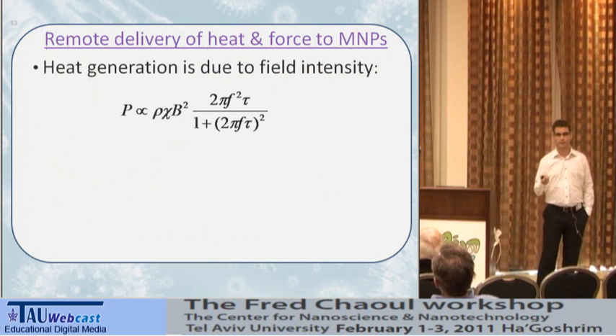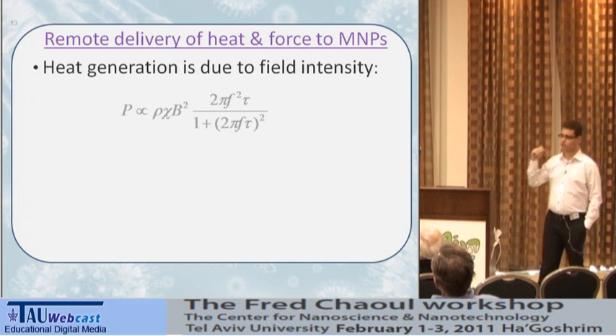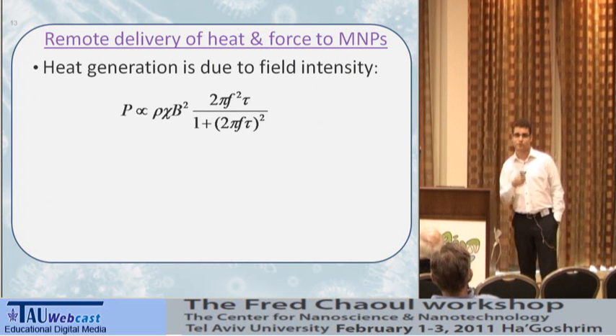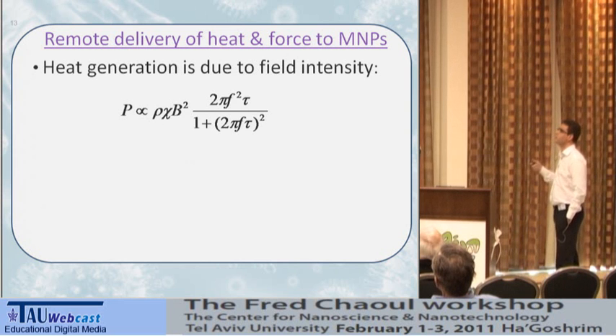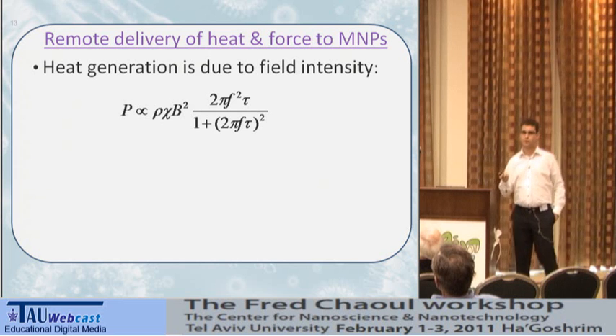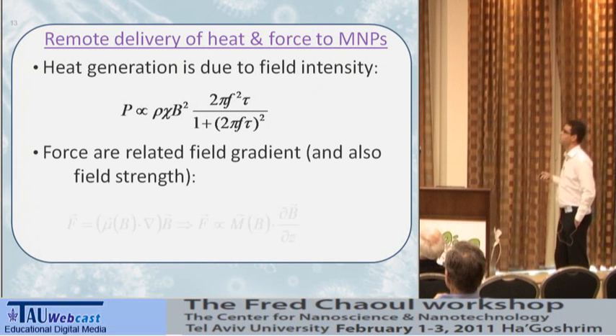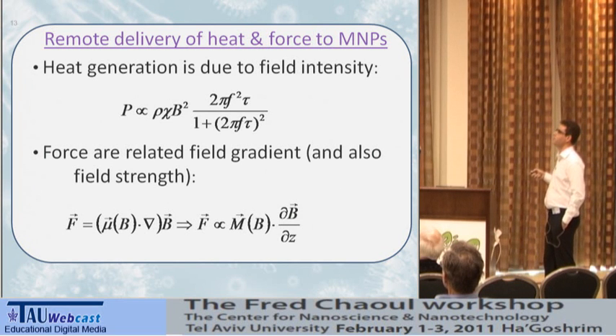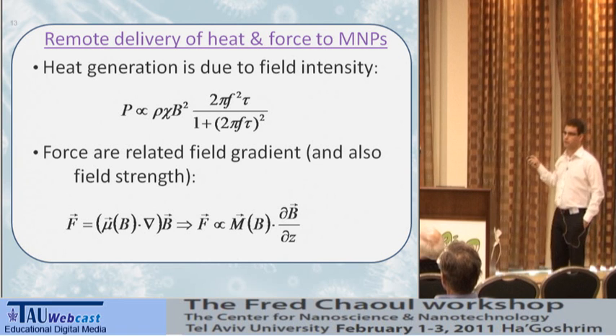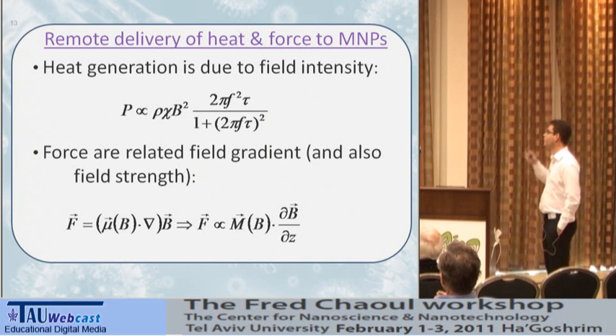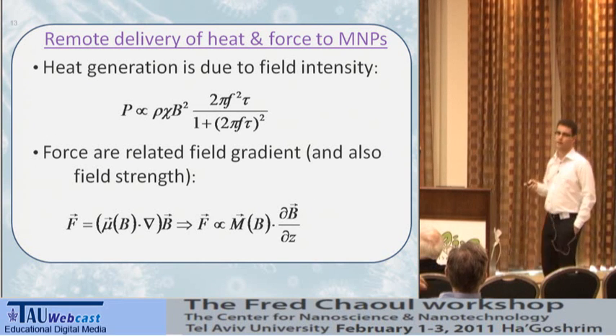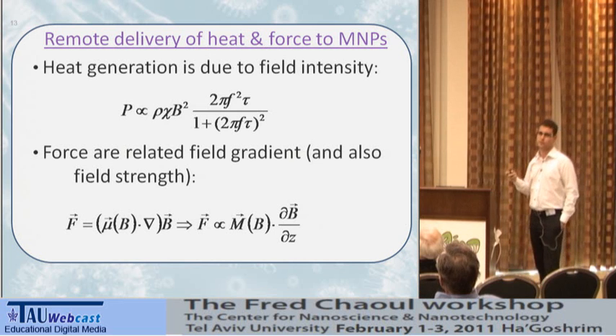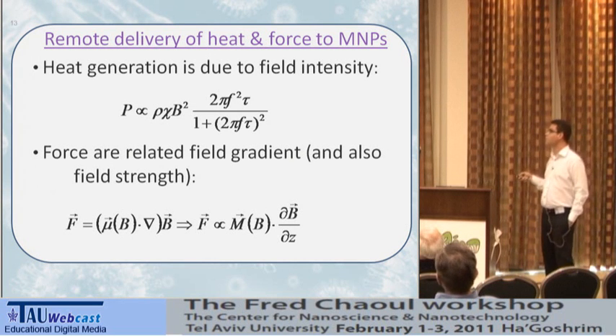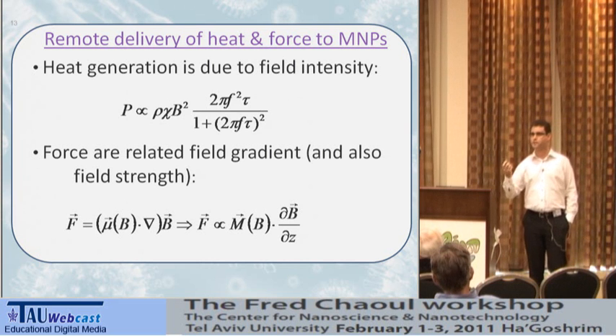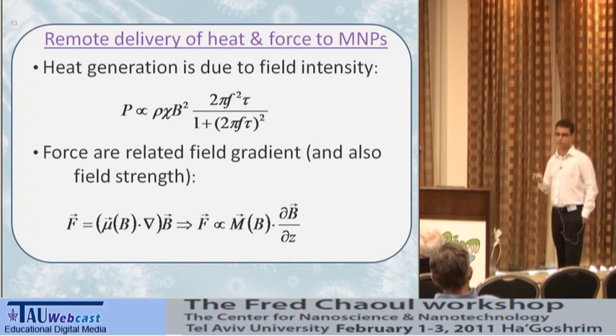So at this point we started thinking about other ways to detect our tumor. The thermomagnetic system was nice. We've seen that it worked, it has potential, but we started to think about other ways. So the first thing we noticed is that the heat was proportional to the intensity of the field, the amplitude squared of the magnetic field. But if we apply a field gradient, a field that changes over space, we can also apply force. We can also pull these nanoparticles toward our coil or solenoid.